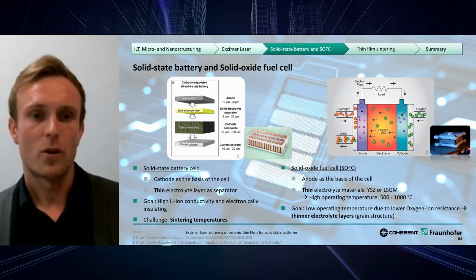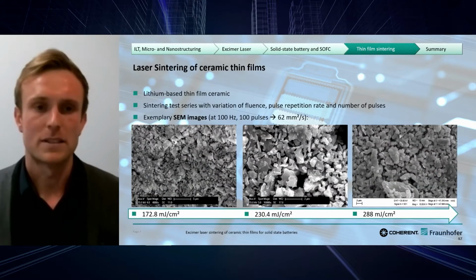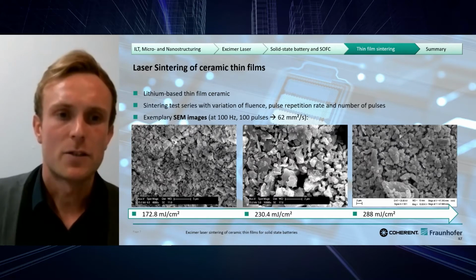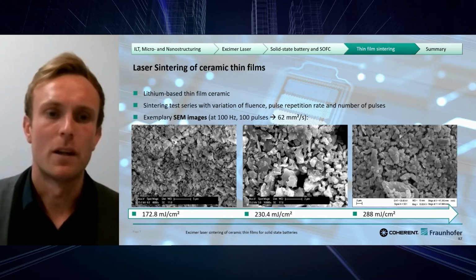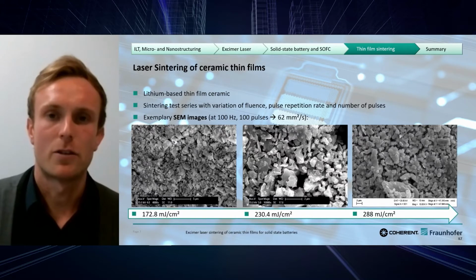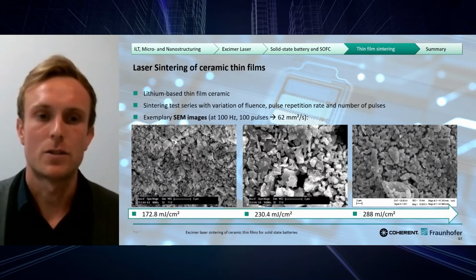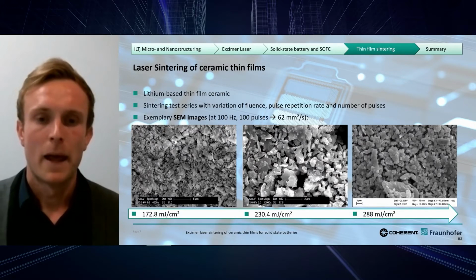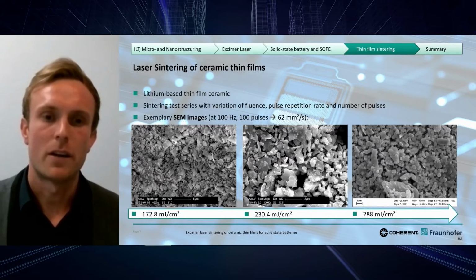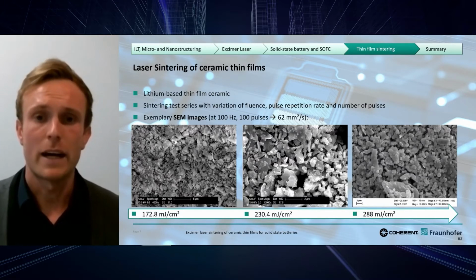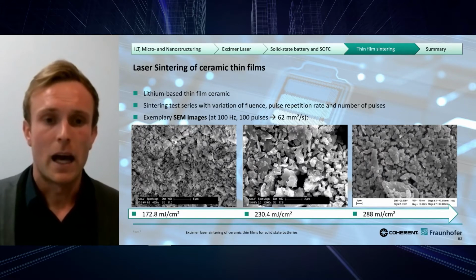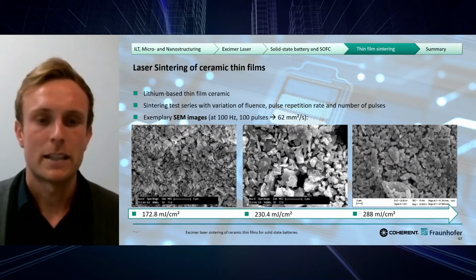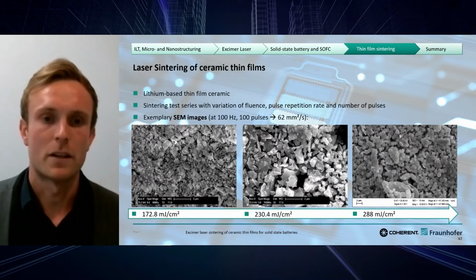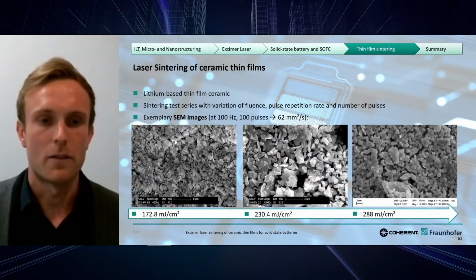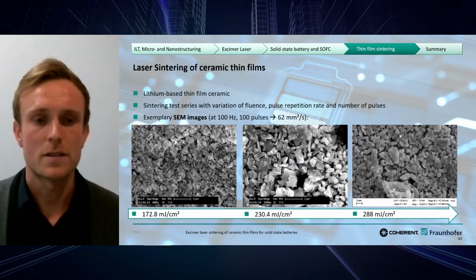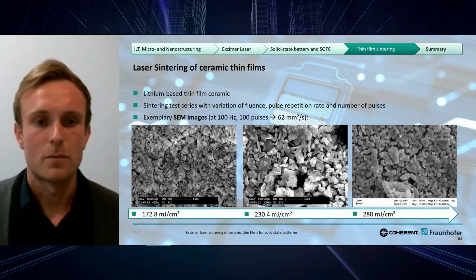And yeah, we did our first trial series of sintering different materials. Here we started with a lithium-based ceramic. So this material can be related to solid-state batteries. In our first trial series, we varied the fluence, the pulse repetition rate, and the number of pulses. And here are some scanning electron microscope images shown with an increasing fluence, starting from the left with the smallest fluence, where the grain structures can be seen.